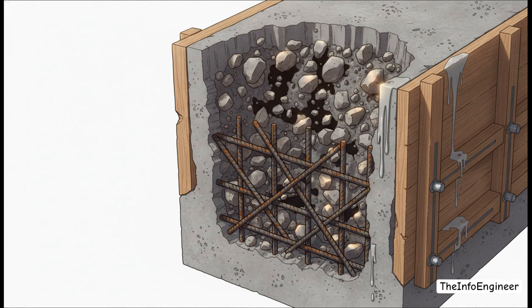Basically, human error during the pouring process dramatically accelerates this chemical decay. The main culprits? Honeycombs. Those ugly, hollow spaces and cavities left inside the concrete mass when the mortar just completely fails to fill the spaces between the coarse aggregate. The causes are pretty clear. Poor workability of the mix is a major one. Then there's improper compaction. Like if you over-vibrate, the mix segregates. Actually, on the flip side, if you under-vibrate, you leave air pockets. Other causes include rebar congestion, where the aggregate just can't squeeze through, leaky formwork that lets all your binding grout escape, and of course, poor aggregate grading.